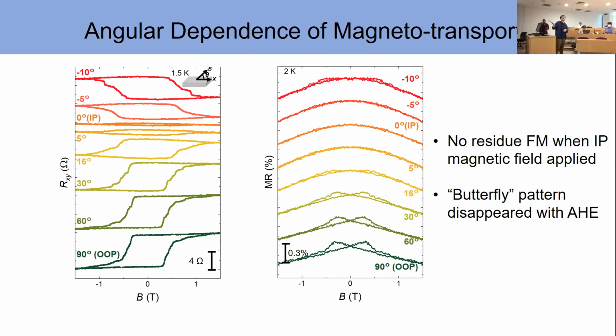Finally, we have our angular dependence of magnetotransport. The observation is that there's no residual ferromagnetic order when an in-plane magnetic field is applied, and the butterfly pattern disappears with it. This means that this butterfly just comes from the scattering of electrons by the magnetic domain wall.